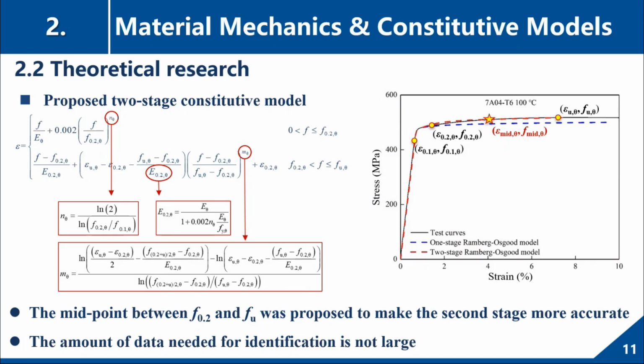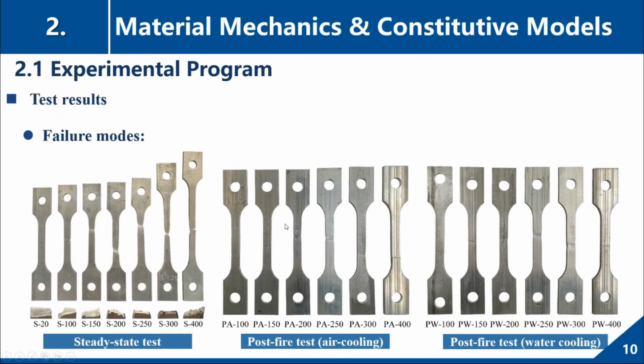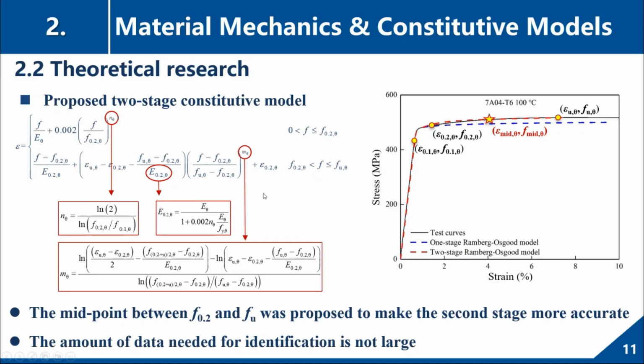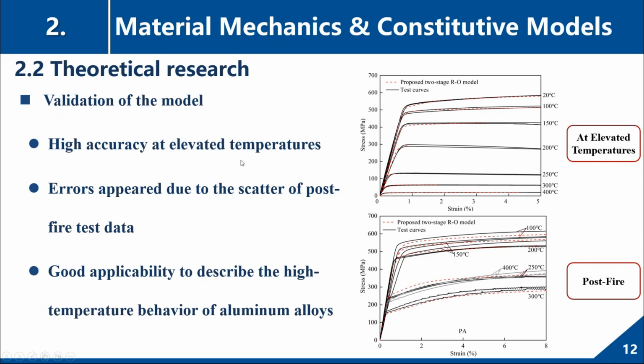Before 1%. But other two-stage constitutive models, for example, some stainless steel constitutive models, adopt epsilon 1 for the second stage. But for aluminum alloy, we cannot use this point because it may fail before that point. So we propose the middle point between the yield and the peak point. And finally, we calibrate the model from the test results and found that the model is rather accurate. And we validate the model through the experimentally obtained data.